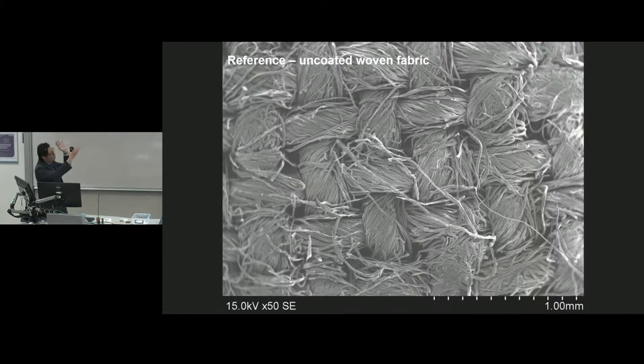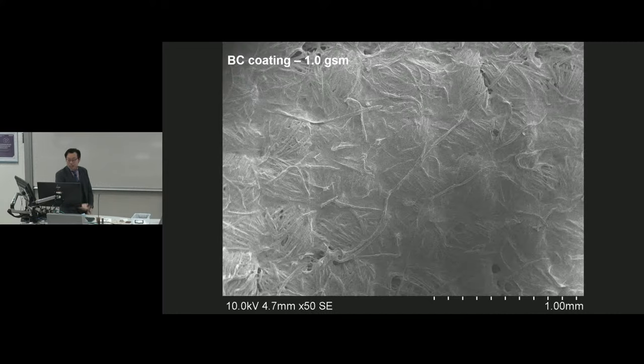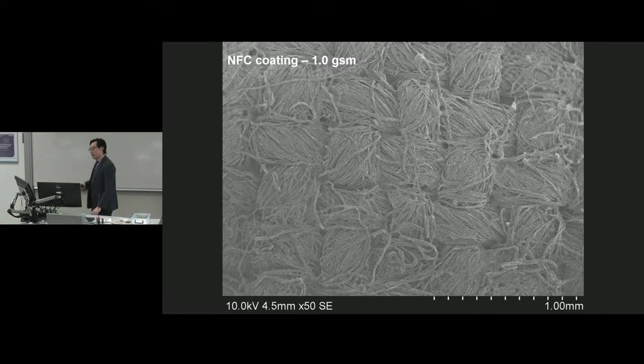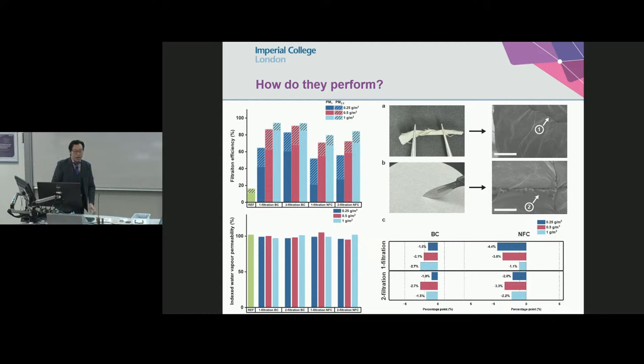So here's how it looks like without the coating, and here's how it looks like with that coating, with just 1 gram per square meter of this material, with that bacterial cellulose coating on top. And the ones with the plant-derived version, it's there, you just don't see them. How did it perform? Well, it actually worked. So here's the uncoated sample. It only stopped 19% of the particles of less than 2.5 microns, true.